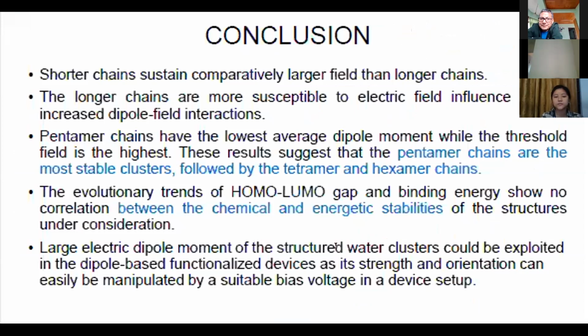collapses. Next, we saw that the pentamer chains have the lowest average dipole moment value, and we also saw that the threshold field value is the highest for the pentamer chain, which suggests that the pentamer chains are the most stable clusters, followed by tetramer and hexamer chains.